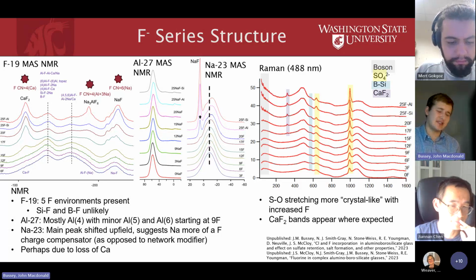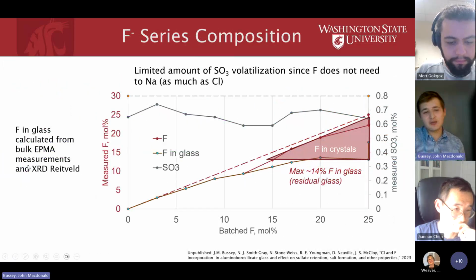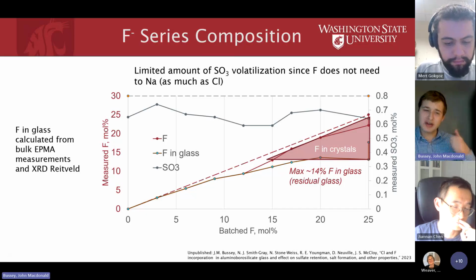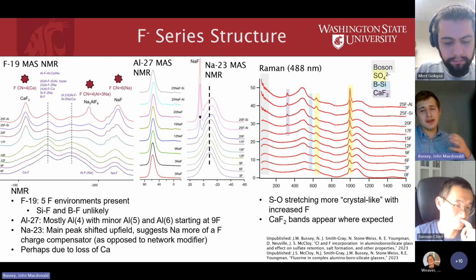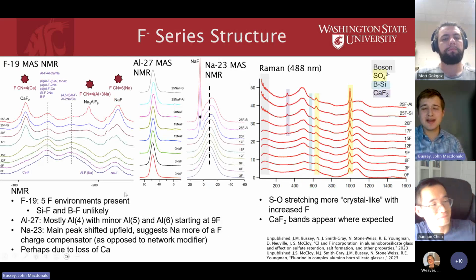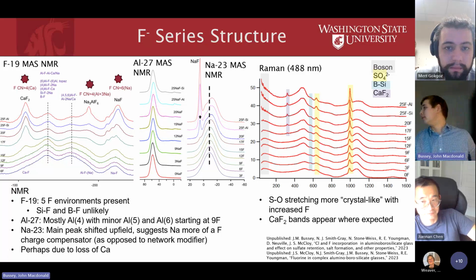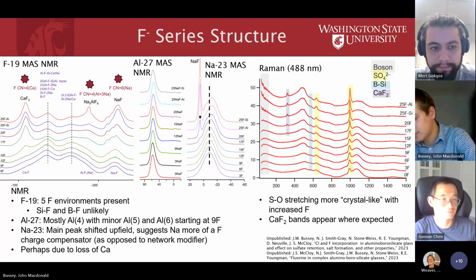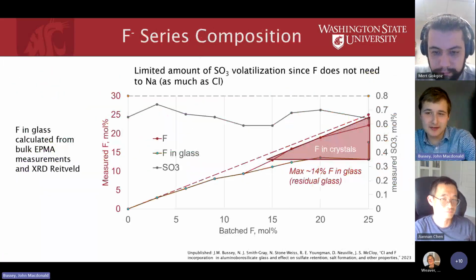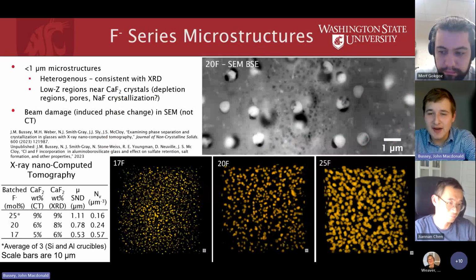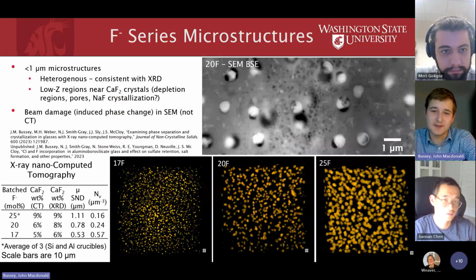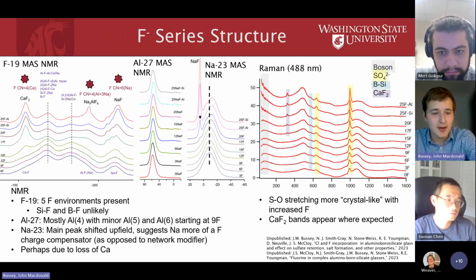That's also interesting because we see from our compositional measurements that I showed on this slide before that the fluorine system pretty much entirely retains the sulfate, which is great news because it's not forming a macro salt phase. However, the fact that we measure it all, but we see it's getting more crystalline, makes us think that in all likelihood, there's some nano crystalline sulfate. So it could be one of these phases we observed in our scanning electron microscopy.